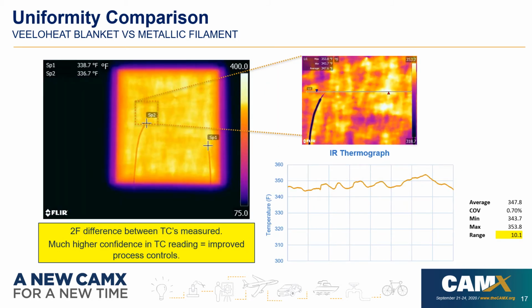So compared to the VeeloHEAT blanket with a continuous carbon heater film, as you can see there's no spacing or cold zones because of that continuous carbon network. Similarly, zooming in on the IR image, we have some analysis here of a line across that. Much reduced, we're seeing a 10 degree range here compared to the 40 of the metallic filament blanket. Again, we did 2 thermocouples laid on the blanket, and we're only seeing really a 2 degree difference between those. So this really leads to a much higher confidence in the TC reading, and ultimately this yields improved process control.